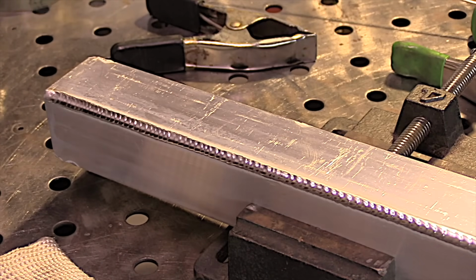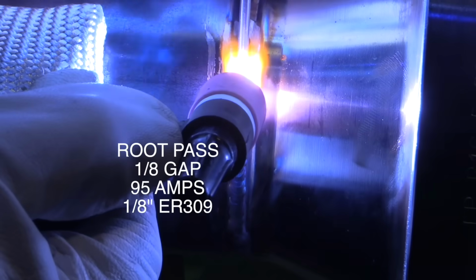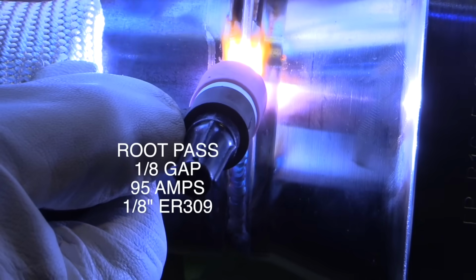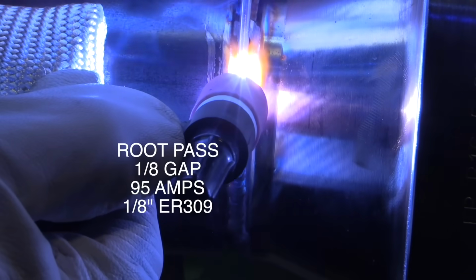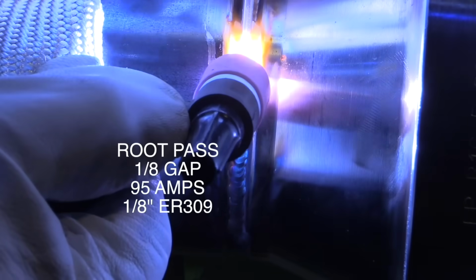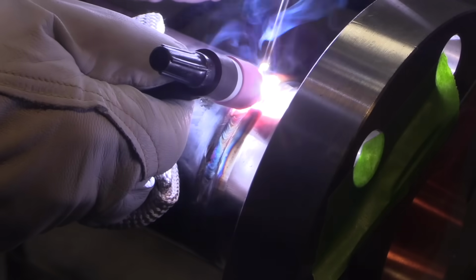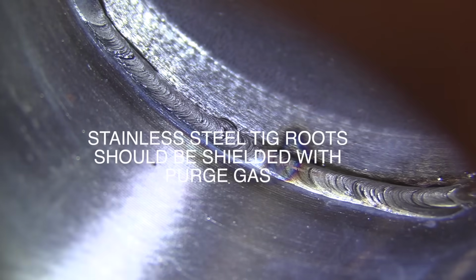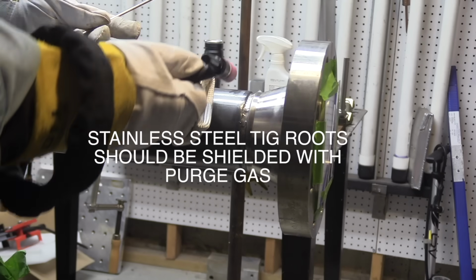TIG welding is also an excellent way to weld pipe. Here I'm welding a stainless flange to carbon pipe using 309 filler, using a technique where I move the arc forward and back, not side to side at all, but just strictly forward and back. The inside is purged out with argon, and that's the result.